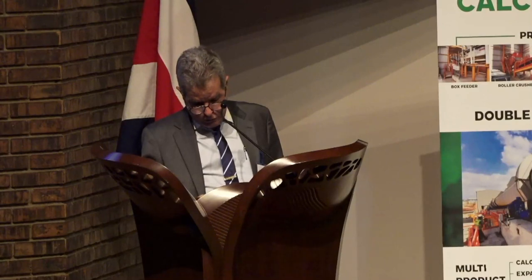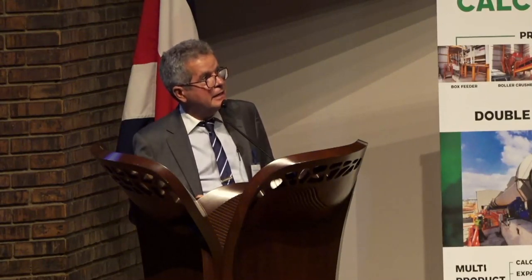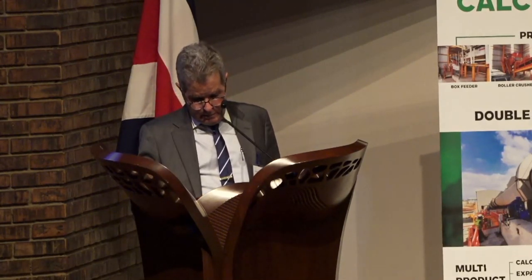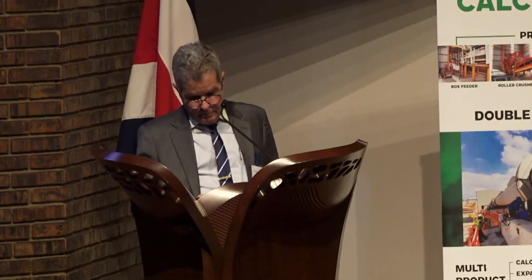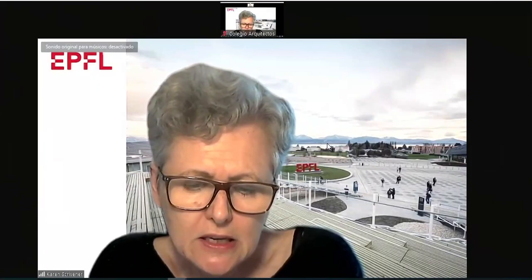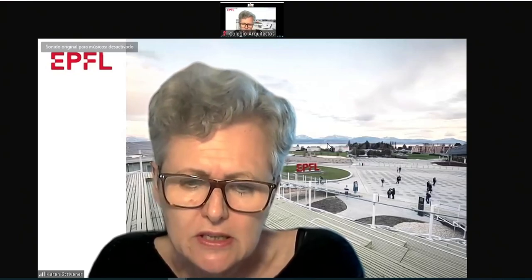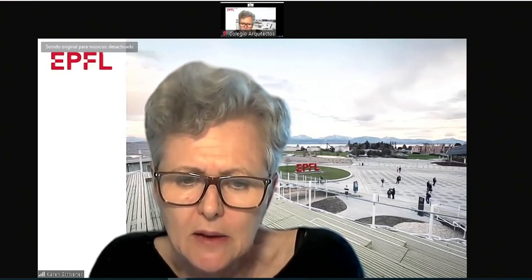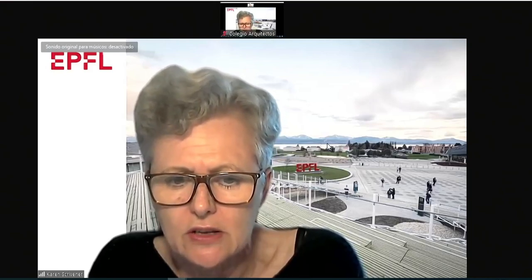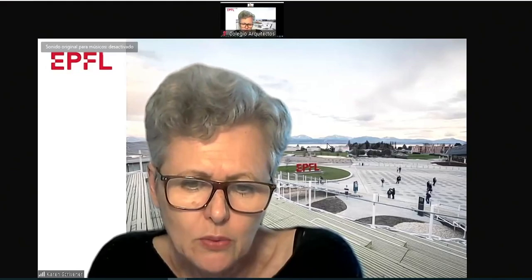Thank you. Next question is, what is the quality control for the calcined clay? Well, I think you'll hear more about that in the other presentations today. There are 2 things you need to look at. You have quite a broad temperature range for the calcination, between about 700 and 850 degrees. It's really all pretty much the same. And the 2 things you need to control, one is under-calcination, and this you can do by looking at the weight loss to check you have no kaolin present.